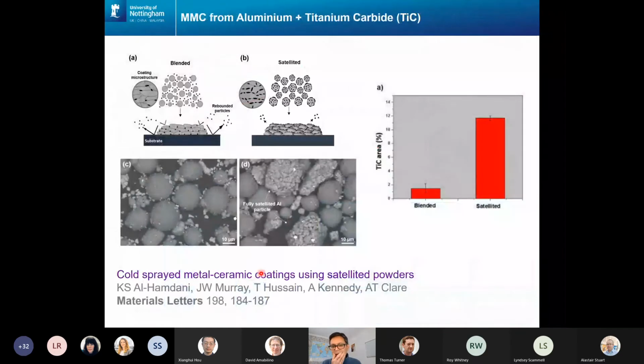My last example here is we were developing MMCs with titanium carbide. So we had commercially pure aluminum powder, and these are titanium carbide particles laced around. And we sprayed it using cold spray. And what happens when we do that? Some of these particles, the titanium carbide reinforcement phase, bounce off and don't contribute to the coating or material deposition.